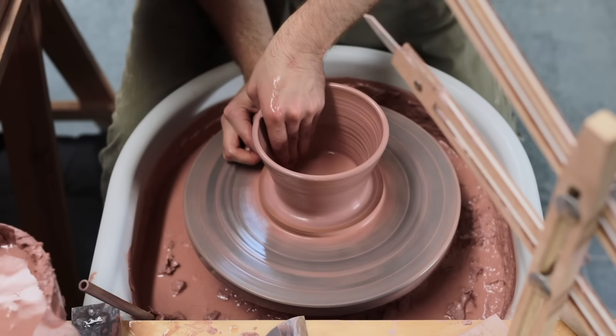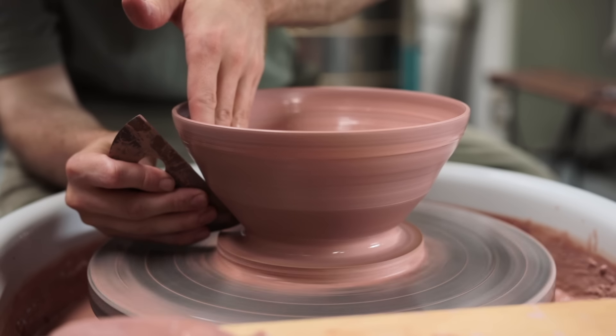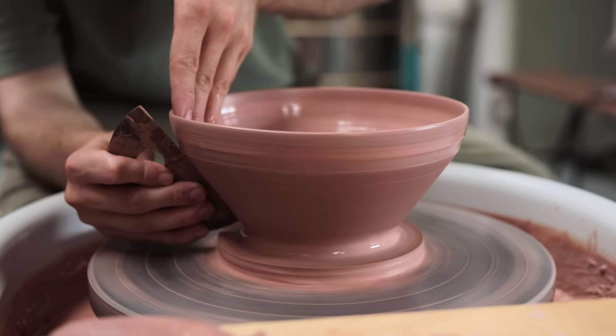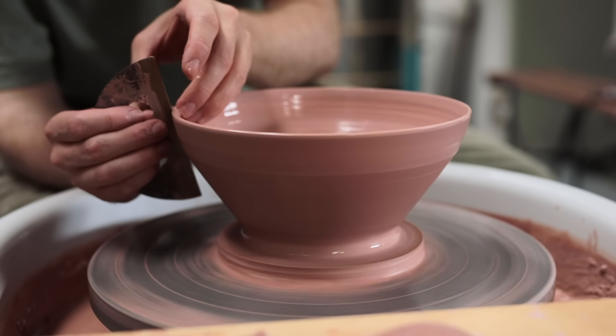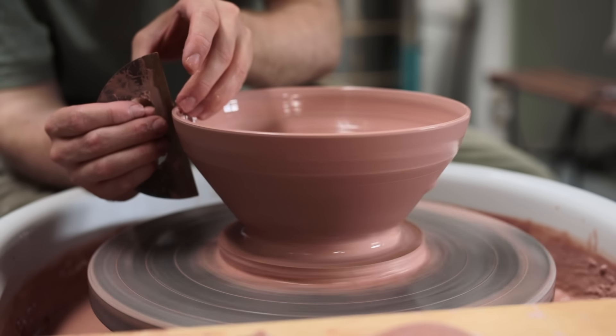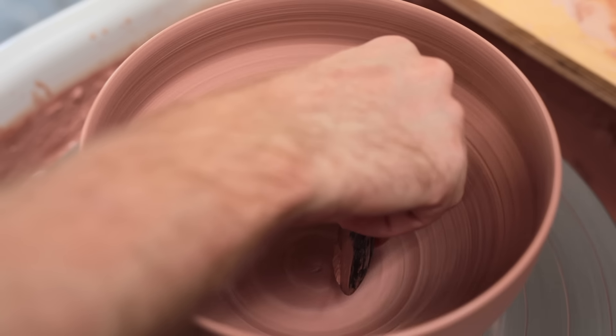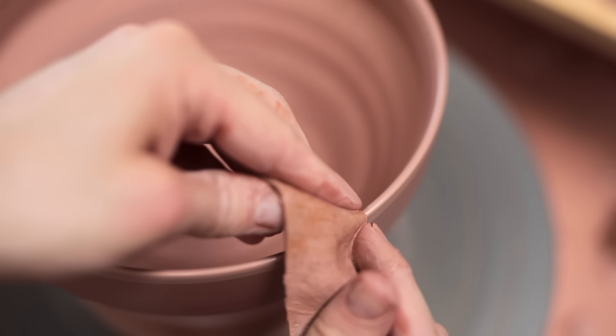The bowl is then gradually formed with slow, controlled movements, with enough water or slip so the spinning material doesn't stick to my hands. Once the shape is approximately where I want it, I'll begin to refine the outside shape of the bowl, removing a layer of slurry that coats it. For most of the shaping, I hold the metal rib close to the profile I want and then push the clay from the inside out against it, as doing so imparts less pressure on the pot and makes the tidying up process safer, as the tool is less likely to catch and pull the pot off centre. I then do roughly the same for the inside, although here my focus is on getting the curve right. And as I'm going to be pulling pouring spouts in the rims of these bowls, I make sure that they are really smooth, even, and slightly on the sharp side.